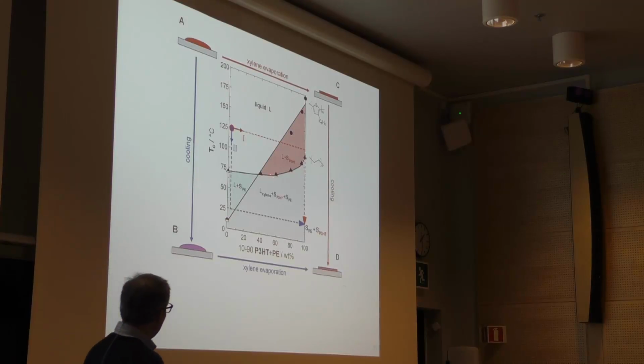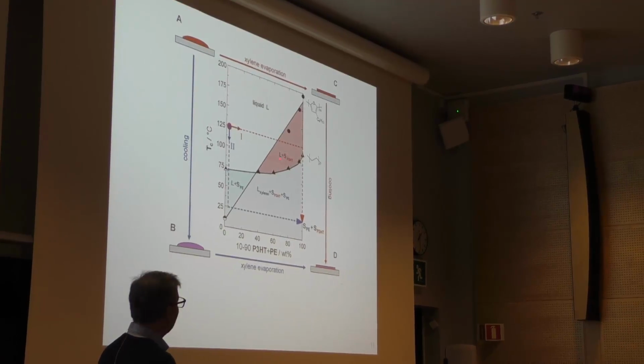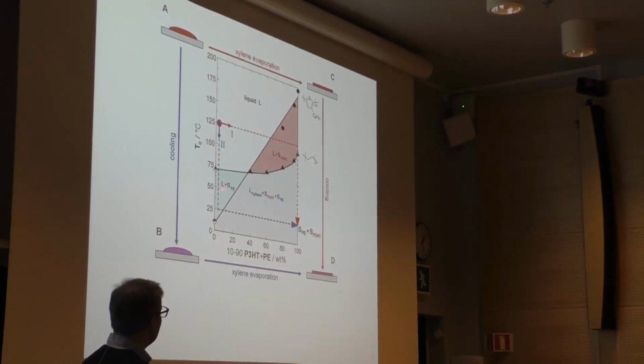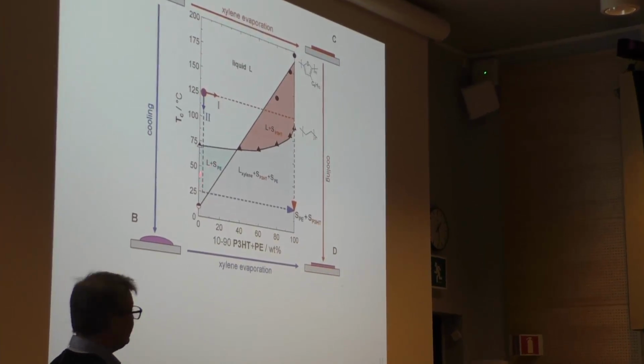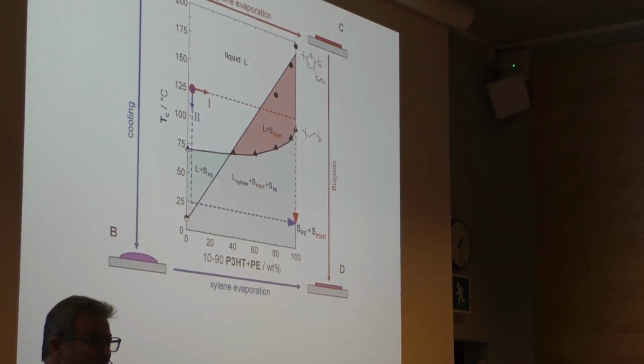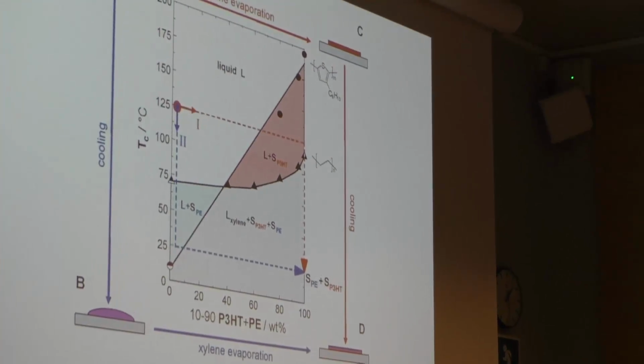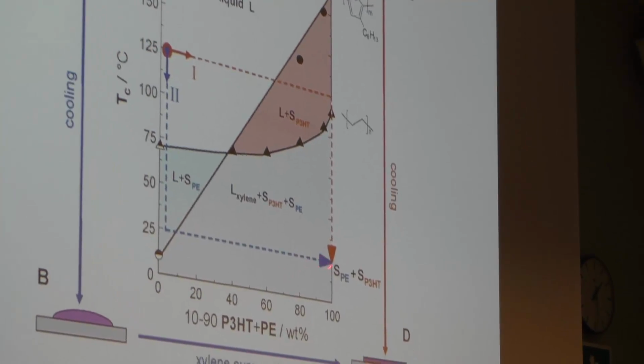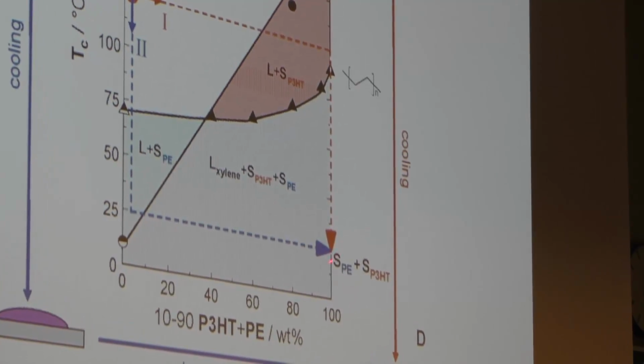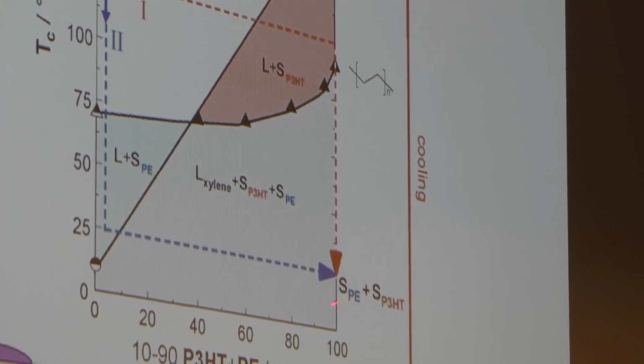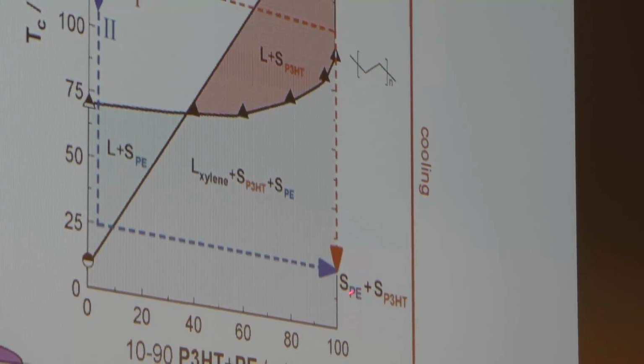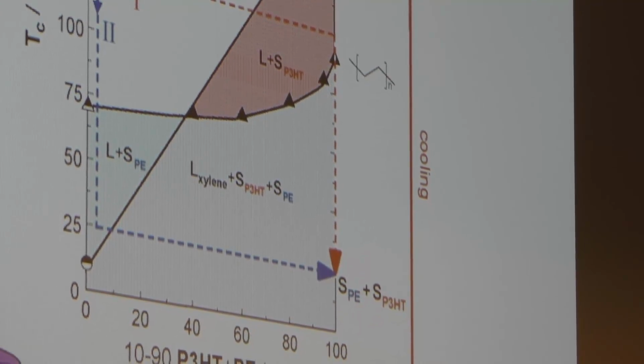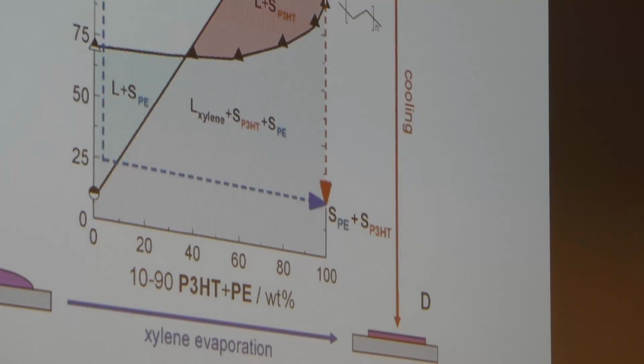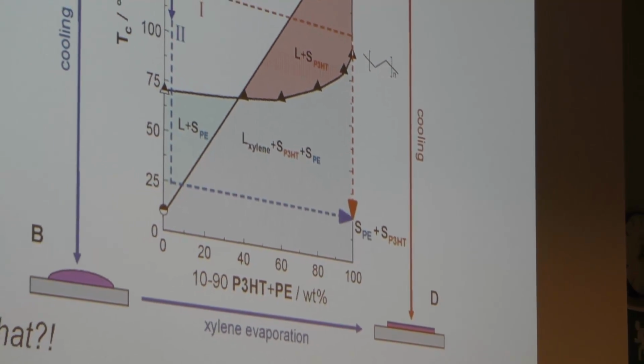So this means that you are going through different paths. In one case you will have the polyhexyl thiophene component crystallizing first. In the other extreme case you will have the polyethylene solidifying first. But in the end you will be down here where the solvent is gone and you are left with a solid fraction of polyethylene and a solid polyhexyl thiophene. So now I hope that you are thinking, so what? And